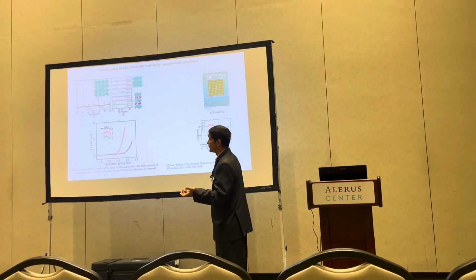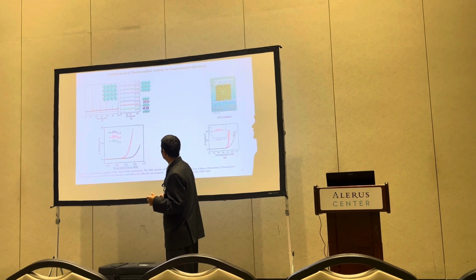Now, how do we know whether the catalyst works better or not? It is represented like this one. Here it is potential on the x-axis, and then current density or current on the y-axis. In the beginning it shows a line parallel to the x-axis, and then it starts curving. The closer this curve starts to this side, to 0, the better the catalyst is, or it works better.